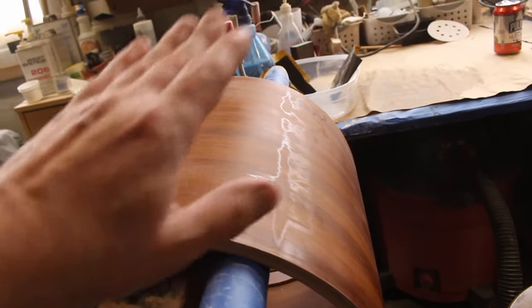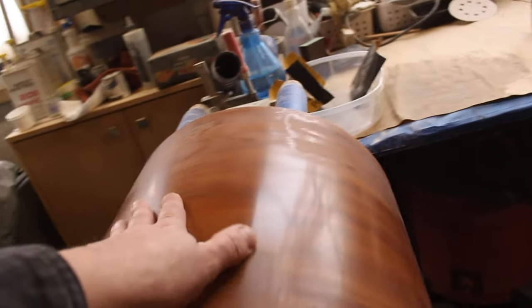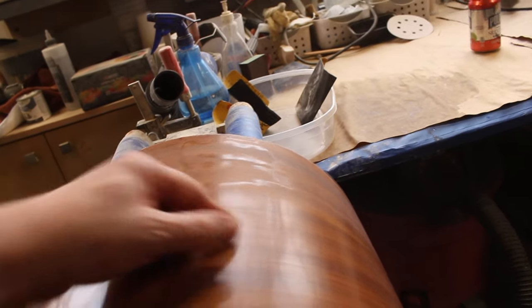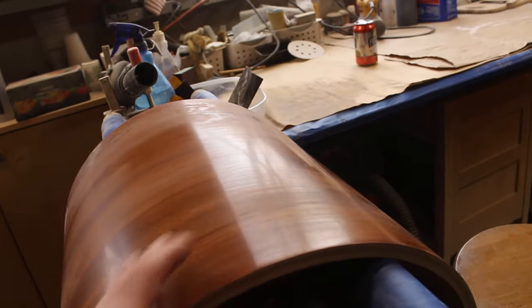Ran into some issues with these drums. Had sanded them to 400, they looked great. Hit them with the 6, peeled off a little more, started seeing some of this. It almost looks like a delamination, but it's not because nothing peels. But it's definitely delineation between layers. We've seen this once before and the buffing wheels took it out. This time the buffing wheels did not.